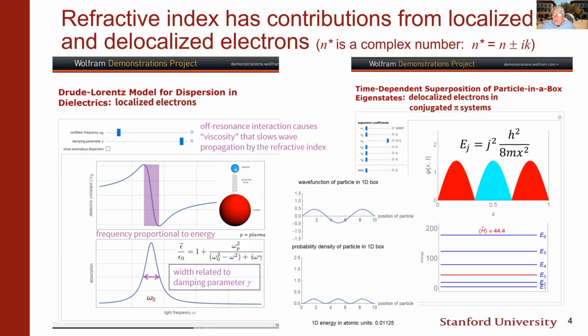So this is appropriate when you get to polyaromatic materials where the electrons can move over large distances, meaning 10 to 100 atoms in length. And so that gives you the absorption bands that give a carbonaceous material basically its black color.